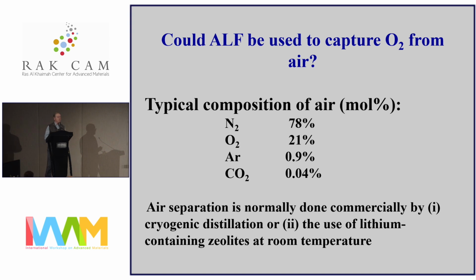Air separation is normally done commercially in two different ways. One is by cryogenic distillation at low temperatures, so you liquefy the air, and then you do a distillation, separating the oxygen and nitrogen based upon their different boiling points. The other way, which is also commercial, is to use lithium-containing zeolites. You might see people with these portable oxygen apparatuses that they carry around. Those normally use a lithium zeolite, and lithium zeolite works quite well. The separation factor for oxygen and nitrogen is about 5 or 6. So it's small, but it's not bad.